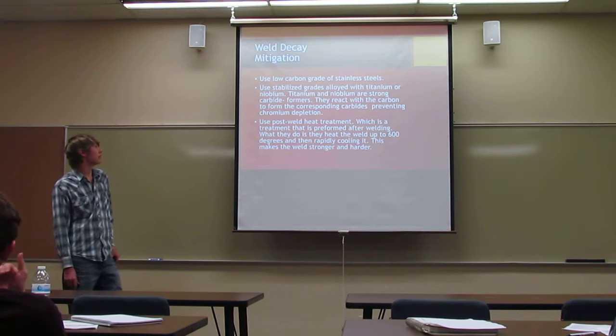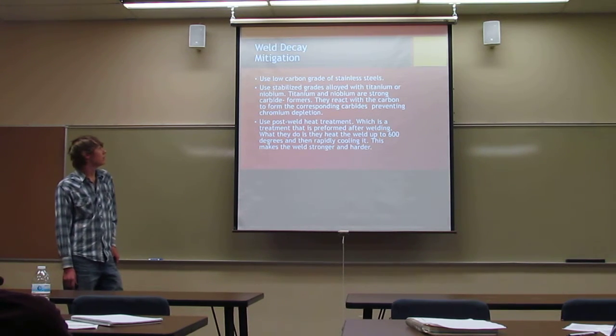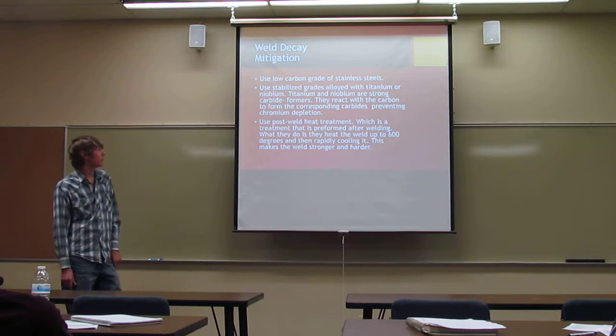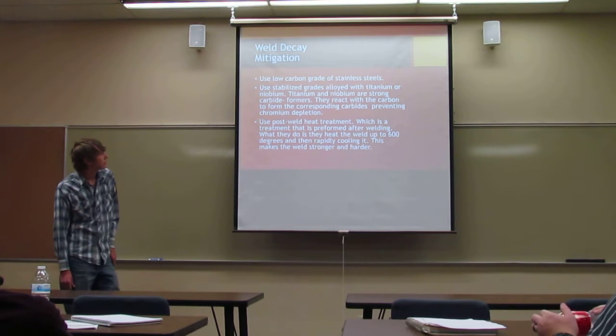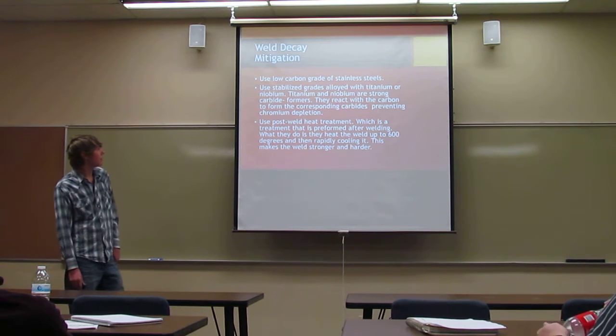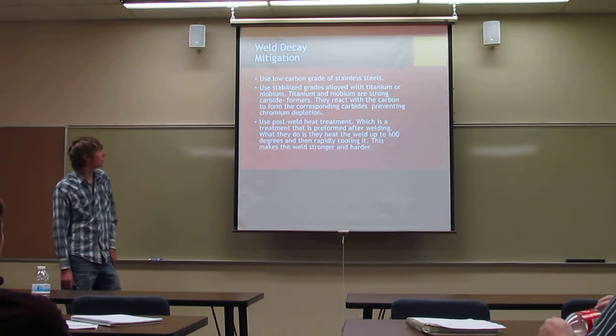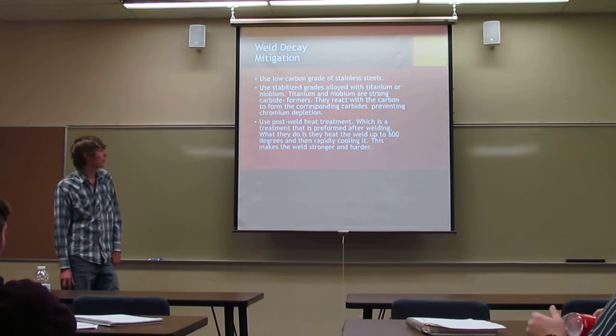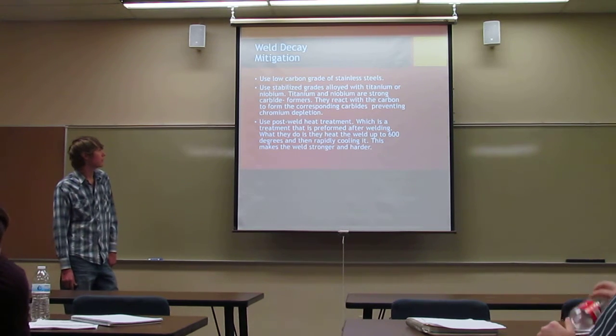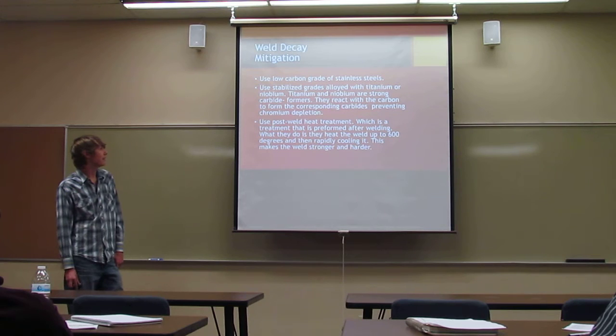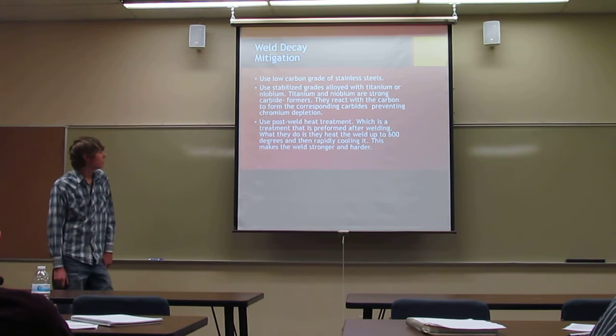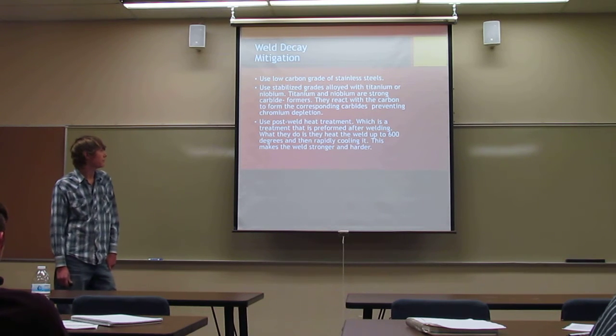Mitigation would be to use low carbon grades of stainless steel, or use stabilized grade alloys with titanium or niobium. Titanium and niobium are strong carbide formers. They react with the carbon to form the corresponding carbides, preventing chromium depletion. Use post-weld heat treatments.